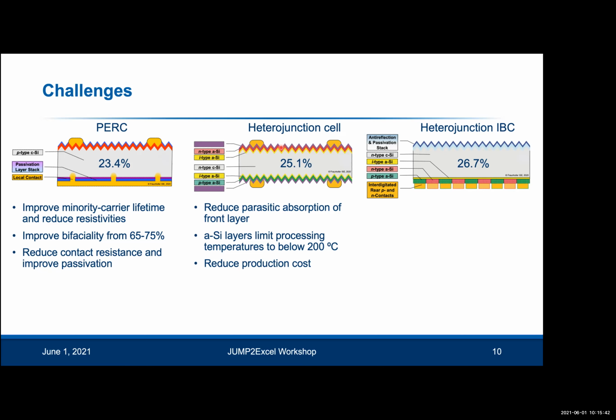So these are limitations that need to be addressed. And another limitation is the fact that you have amorphous silicon. If you heat amorphous silicon up to above 200 degrees Celsius, you would then crystallize that and change the device structure. So that's another limitation, which, for example, prevents using industry standard metallization methods.